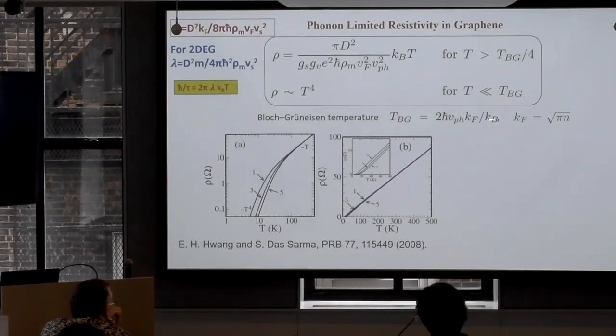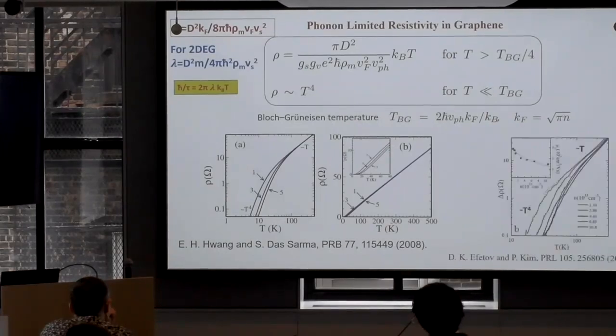The Bloch-Gruneisen temperature is nothing other than this quantity. It's the energy of a phonon with 2kF scattering, because the most dominant resistive scattering is an electron going in this direction and reversing its path. So that's 2kF, the most dominant scattering, and that's the temperature scale. So we should see this. We made this prediction and produced results, and this is their experiment. I'll just say it agrees quantitatively with this theory.